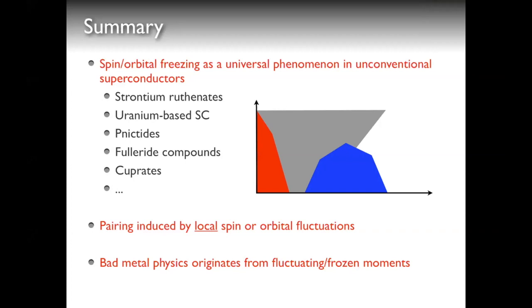But the interesting point about the square root of omega is that we are not talking about extremely low temperatures here. The interesting fact is that at relatively elevated temperatures, over a very wide temperature regime, maybe 1 decade, you can roughly see a square root scaling in very generic multi-orbital systems: 2 orbital, 3 orbital, 5 orbital. And of course, as you move away from this optimal spin freezing crossover point, you will see different exponents.